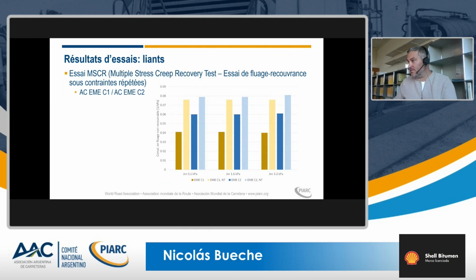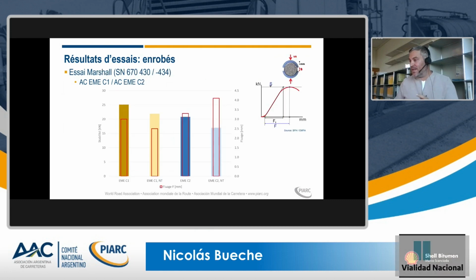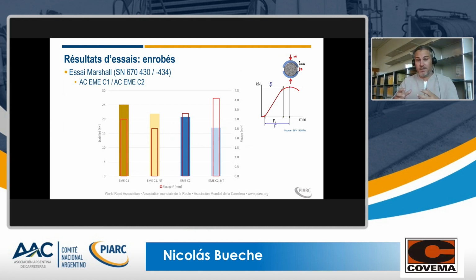This is the rest of the results for the multiple stress creep recovery tests, where we could really see some difference between warm and hot mix asphalt. And then we made some more classical tests as well. There is no Marshall limit value for high modulus asphalt, because we look at rutting, stiffness, etc. But anyway, we did the test because it's a test where we have some experience values, and we can make some comparison.